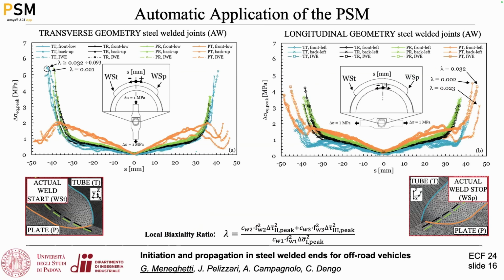After running the linear elastic finite element analysis, the first question is, which will be the crack initiation point? You have so many points in competition, and the first way to test a fatigue model is to see if it correctly predicts the crack initiation point among those in competition. So we have to plot the equivalent peak stress along all the lines.